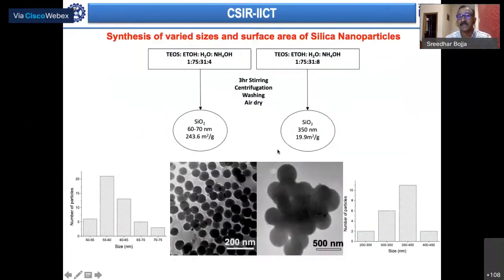But there is something different here. These nanoparticles have a large surface area, which makes them attractive for catalytic applications. We worked with two different protocols, with a difference of only ammonium hydroxide, 4 units versus 8 units. With this small difference, you can synthesize these materials in two different sizes, 60 to 70 nanometers and 350 nanometers.